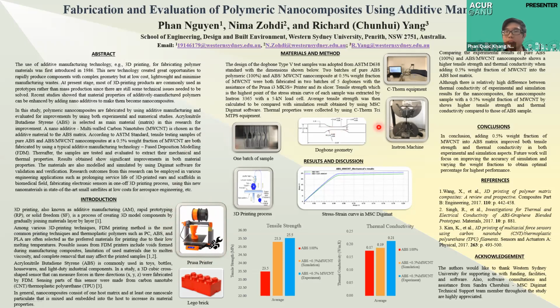For extracting the tensile strength of the sample, we use this Instron machine. The sample can be mounted vertically in the middle here, and the machine will gradually stretch one end while fixing the other end until the whole sample is totally broken. On the other hand, the thermal conductivity was measured by this C-Therm equipment. The box here is the controller box, and all of the measured data will be transferred to the computer for later analysis. Thereafter, the material will also be modeled in MSC Digimat for the simulation result. And this picture here shows the simulation result that I obtained from MSC Digimat. The green curve is for the polymeric and the blue curve is for the nanocomposite.